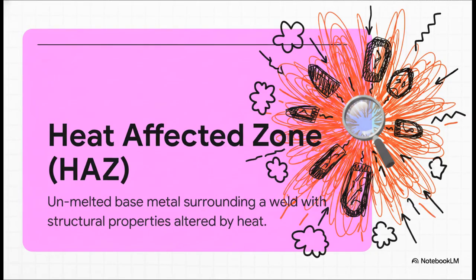And here's a really interesting twist. The danger isn't even necessarily in the weld itself. The focal point of all this crazy tension hides in a specific area called the HAZ, or the heat-affected zone. This is just the strip of base metal immediately surrounding the weld. It didn't actually melt, but it got so shockingly hot that its internal structural properties were fundamentally altered. That specific zone becomes the ultimate battleground where all those invisible pulling forces concentrate.